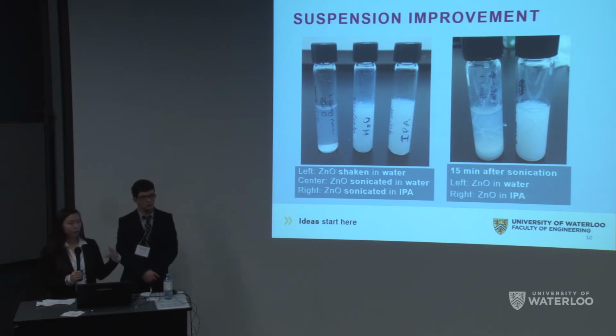Although the water and IPA solutions look the same, they aren't, because after 15 minutes, the ZnO in water actually sunk, which is on the left image. So therefore, for the relevant duration of our coating step, which was 10 minutes, we chose to use ZnO and IPA.